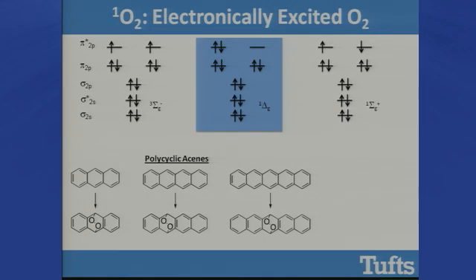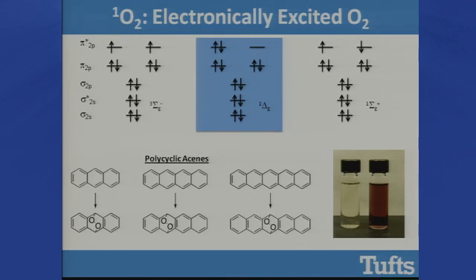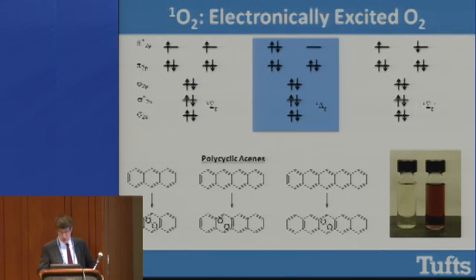It turns out that there's a number of people in the organic semiconductor field that want to take pentacene and make really good transistors out of it or other types of devices out of it. And this reaction is actually a real problem for people who want to use pentacene to do that, because it's so efficient that you can see here, this is a solubilized form of pentacene in organic solution. If you go to lunch and leave it exposed to light and oxygen for a little while, it's totally bleached by self-sensitization through this cycloaddition reaction. Someone like me looks at this and says, clean reaction, really fast, and dramatically changes the optical properties of this molecule is something that we think is pretty exciting to use.